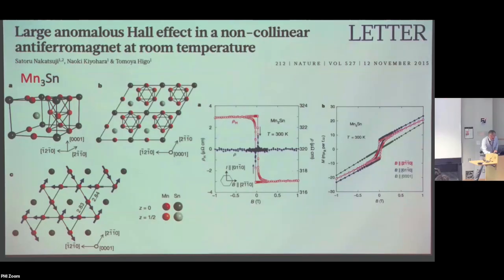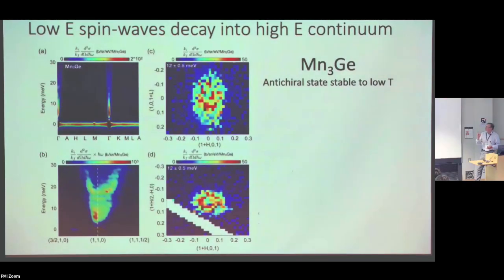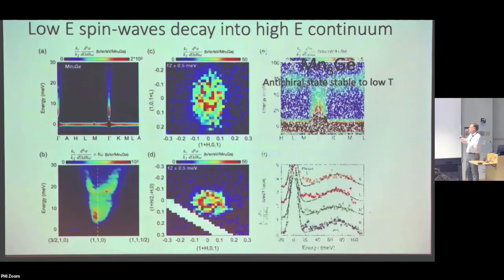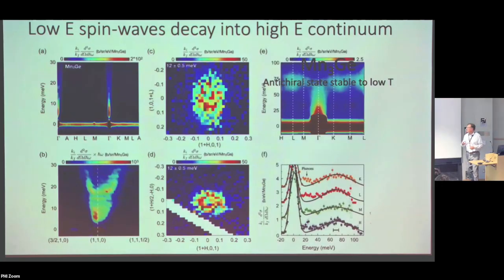But we were interested in trying to understand the magnetic interactions between the sites and understanding whether it was two-dimensional or three-dimensional. And for that, we employ our inelastic scattering techniques. In this case, the energy range is quite different. We're up to hundreds of milli-electron volts. Yesterday, we were working down at micro-electron volts. So we changed the instrument, and now we're up in this range.